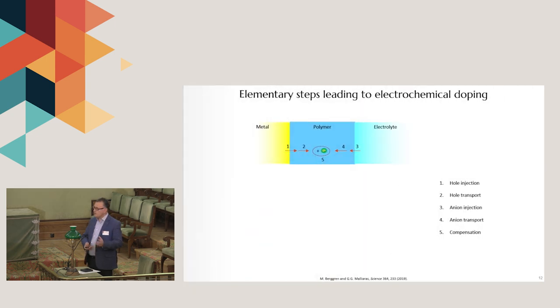So what my group has done is we took that know-how and transferred it to electrochemical phenomena. In a similar fashion, when you dope a conducting polymer or any conjugated polymer for that matter, you have the polymer at an interface between an electrolyte on one side and a metal electrode on the other. And the following physical phenomena need to take place for it to become doped. So an electronic charge, typically a hole, gets injected from the metal to the polymer film. It needs to be transported through the volume of the polymer. At the opposite side, an ion gets injected and transported, and the two combine to give rise to the doped state. And we started putting together energy level diagrams.